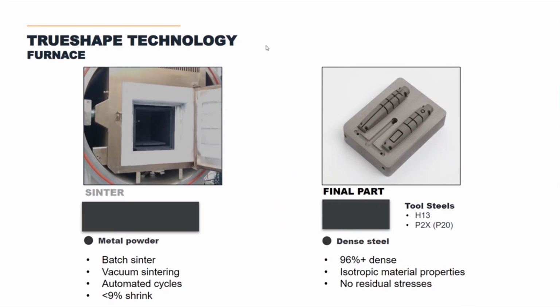Other sinter-based processes shrink more like 18 to 20%, but still this is where we're losing our tolerance. It's how closely can we predict how much this part is going to shrink during this process. But even with that shrinkage, we're able to achieve that plus or minus 1 thou per inch. The result is a part with no residual stresses. It's a dense isotropic material.